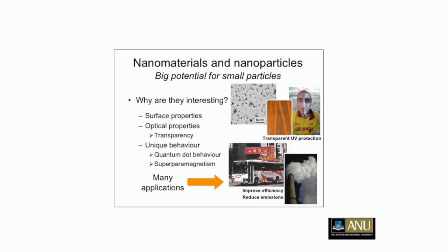Again, we can use these nanoparticles of zinc oxide or titanium oxide in paints. For example, wood gets degraded because of the UV radiation in sunlight. So now if you have a paint which only absorbs the UV light but doesn't absorb the visible light, that means you can still see the patterns in the wood, but the paint is protecting the wood, thereby the wood can last for a longer time, which is very environmentally friendly as well.